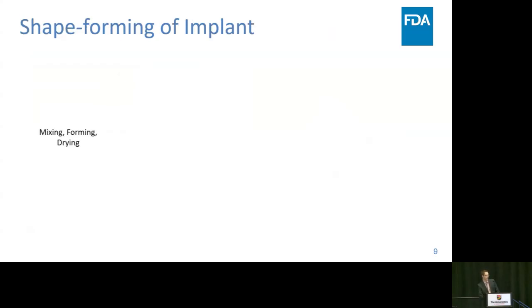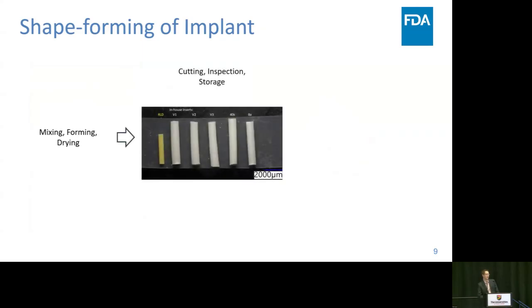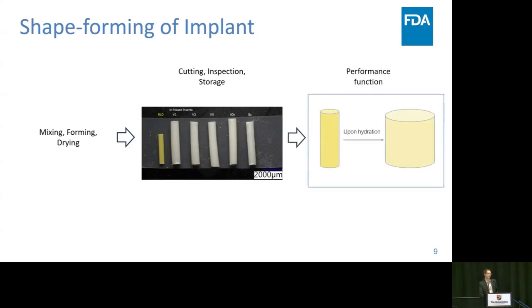And then we come to the manufacturing process and how you make the implants. So first, there's a mixing step, and then you shape form the implant into the shape that you want, and then you have to dry or cool the implants to equilibrate them. And then from there, you do cutting and then QA and store them. So these are an example of the commercial insert, as well as some of the in-house inserts that we made. You can notice that in some cases we opted to exclude the dye, and we also made them at different dimensions to simplify the study and look at various different aspects of the process. And then from here, it leads to inserts that are able to swell and accomplish the features that we talked about.